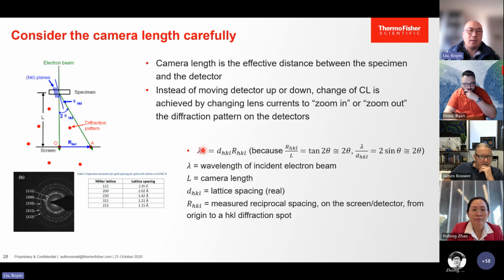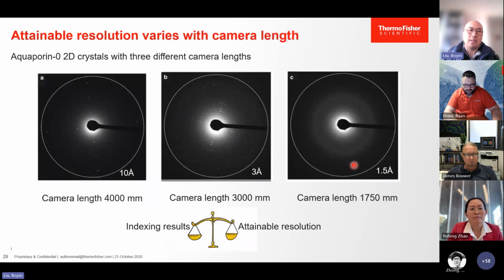You can see from the equation that the bigger the camera length, the bigger the R, the bigger the reciprocal spacing, meaning that if you use a longer camera length, then you're going to lose some of the high resolution diffraction patterns. So in order to illustrate this difference, I'll put an example here. This is an example of aquaporin 2D crystals. With a camera length of 4,000 millimeters, you can see that you have very well separated diffraction patterns, but your resolution cutoff is only 10 angstrom. You're not going to get very good resolution for this diffraction. And then if you lower the camera length to 3,000 millimeters, you get more diffraction patterns here, and the resolution cutoff is 3 angstrom. And if you keep lowering the camera length to 1,750 millimeters, your sample can diffract up to 1.5 angstroms,